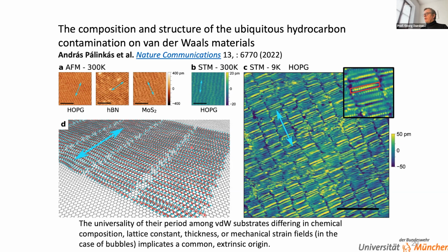And they see this type of contamination, where they see a bit of periodicity in there, on HOPG, MoS2, hBN samples quite a bit, and they also come to the same conclusion that the contaminations have an extrinsic origin; they absorb onto the substrates. After a while, they actually leave the samples in the ambient in the lab for a while to get these images. So this story seems to be consistent, and I think it's very interesting for everybody who works with those materials and with their surface properties.